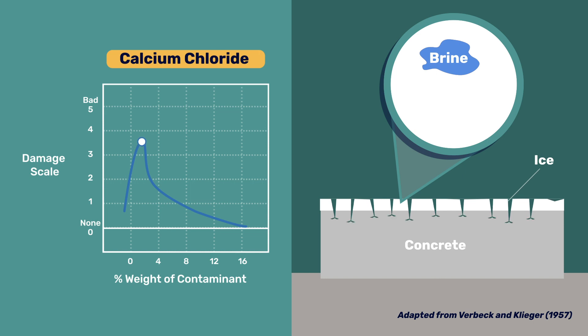On the other hand, too many such defects weaken the ice layer too much, and reduce the elastic energy that can build up upon cooling and before cracking. Therefore, beyond the pessimum, the cracking releases less energy, so damage decreases as the contamination level continues to increase.